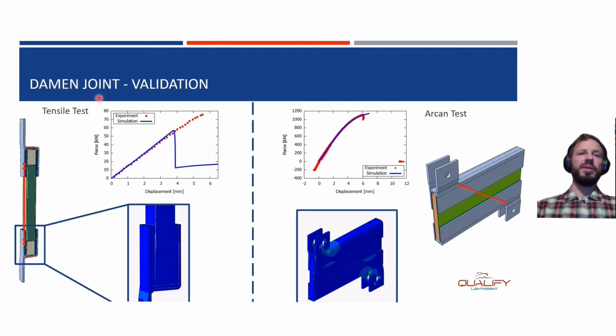On the top side here, you see the force displacement curve in comparison, experiments versus simulation. As you see, the behavior is captured relatively well, slightly underpredicted due to a conservative modeling approach. For the displacements, it's to be noted that we considered two points here in the specimen for one simple reason. In experiments, you have so many phenomena that are included, the clamping, some slippage, some machine stiffness, that we don't want to simulate with FEM, it takes too much time. So we just looked at the virtual extensometer results here.